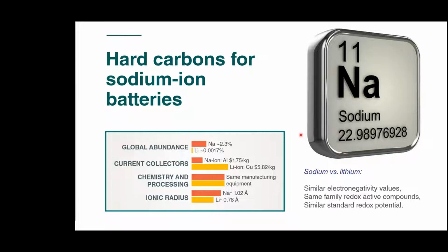We can replace other components inside the battery, such as the current collector, for cheaper and more abundant alternatives. But in terms of the chemistry and the processing, because they are quite similar, it means there's no extra cost required to replace lithium technology with new sodium technology. One of the drawbacks, though, is that sodium has a higher ionic radius. So that means in terms of the projected energy density, we can't necessarily reach as high as we could for lithium-ion technology, but that means it's more suited for stationary storage applications.